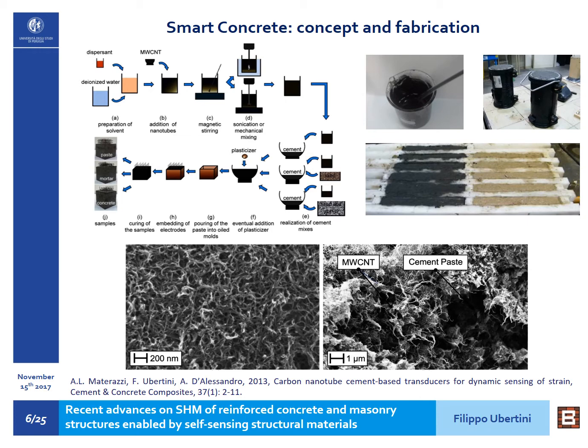On the top right of the slide you see a few pictures of concrete specimens, whereby the white specimens are normal concrete ones and the dark specimens are specimens with nanotubes, where it should be remarked that only 1% of nanotubes is used in this case. So you see how significant the change in color is, achieved with such a small amount of nanotubes, which is very remarkable. And then on the bottom part of the slide you see SEM pictures showing the nanotubes creating a very nice network when dispersed in water on the left, and on the right you see the nanotubes creating the network when they are inside the hardened cement matrix.